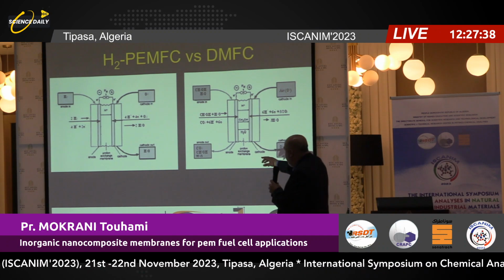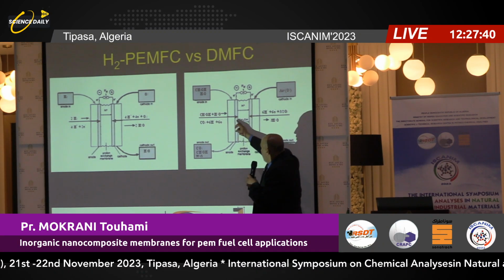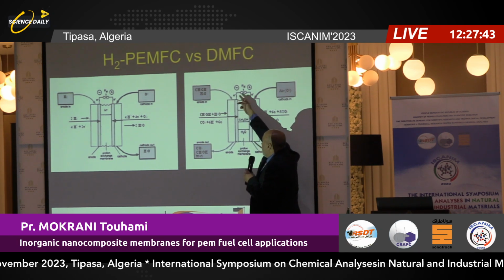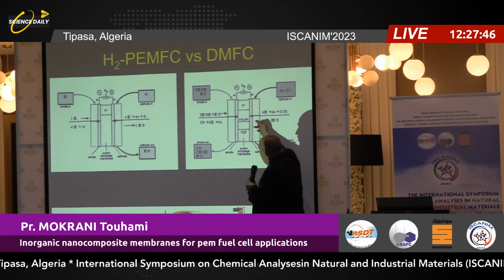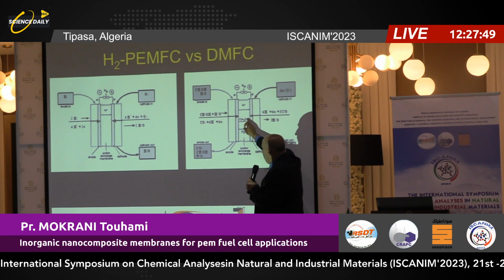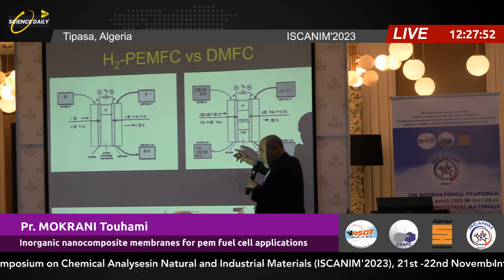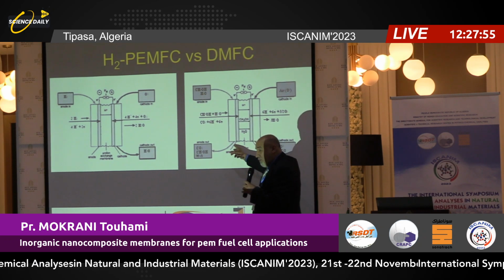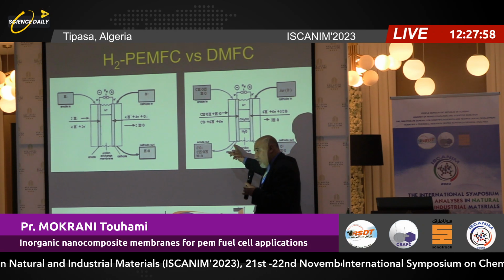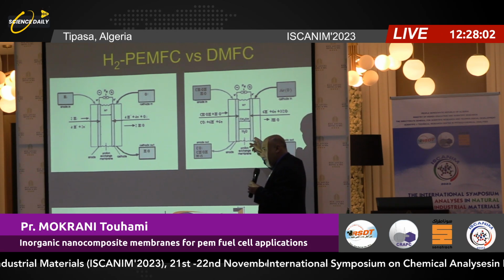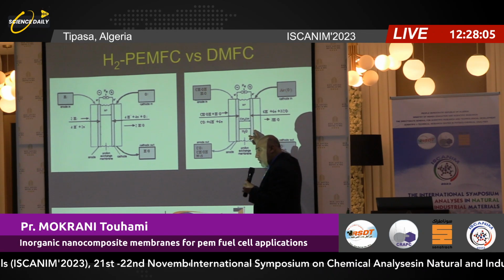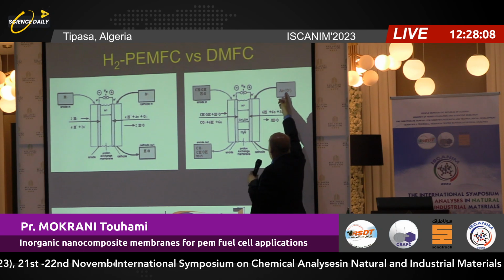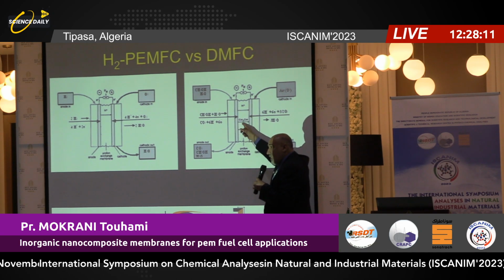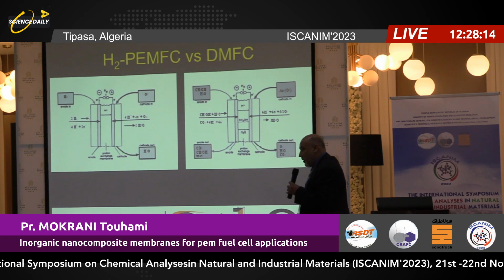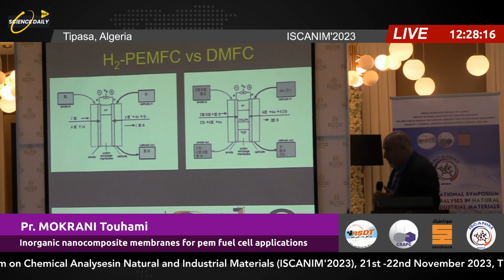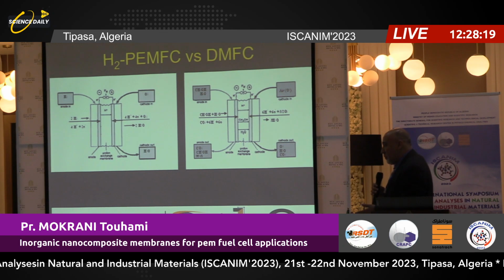In this reaction, that's methanol, so you have protons and electrons. The electrons we capture in the external circuit, the protons will travel through the membrane, but also we have methanol going through. The problem with this: at the anode we have platinum, which is very good for methanol oxidation. The problem is we also have platinum at the cathode. So if methanol crosses the membrane, there will be a competition between oxygen reduction and methanol oxidation at the cathode side, and the efficiency of the cell will drop. So that's why we need to do something to block this methanol from going through.